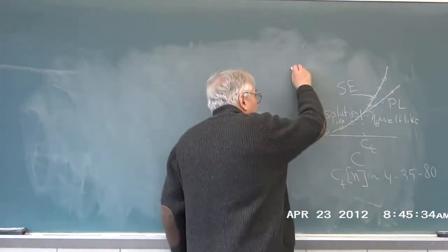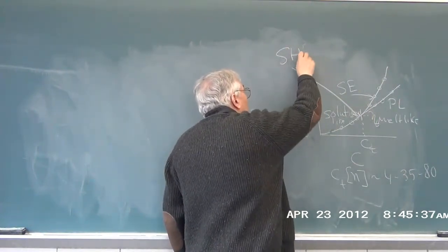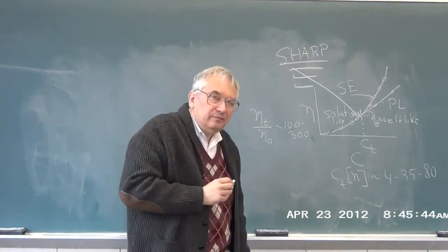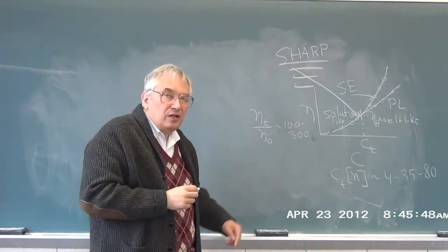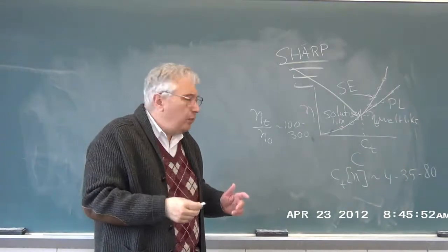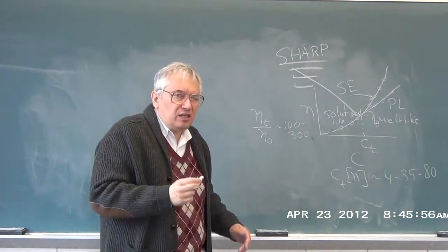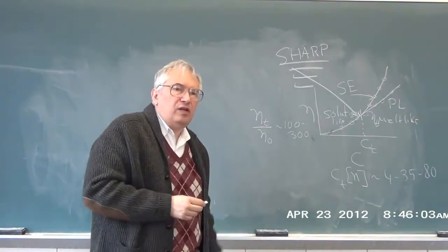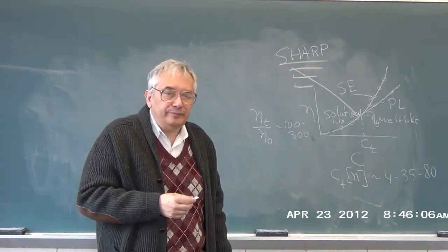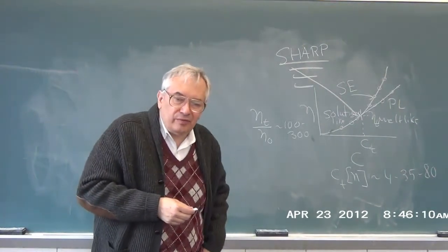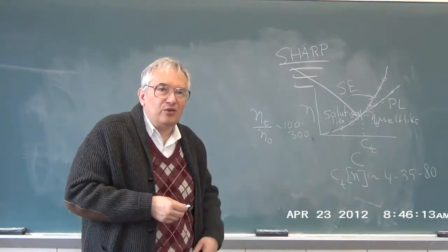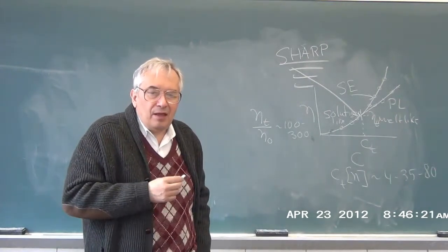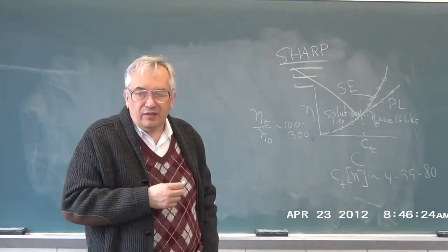This crossover, by the way, in viscosity, is sharp. So the answer is there is a sharp concentration. In the cases we've looked at, it's always found at about the same relative viscosity. That was an about, not an exact. And therefore, you know roughly where to look whether something interesting is going to happen or not. Okay, thank you. Of course, if you actually have a system and you can't get a lot of data points, you may be less happy with this statement. You do need some decent number of measurements to see something. Okay, so that is an actual crossover in the viscosity.